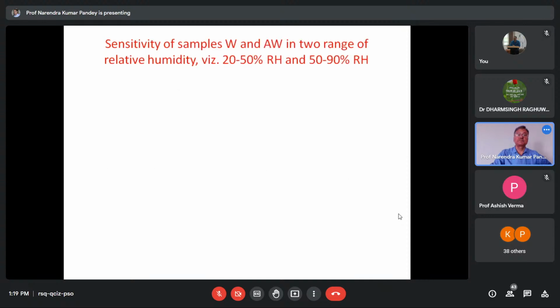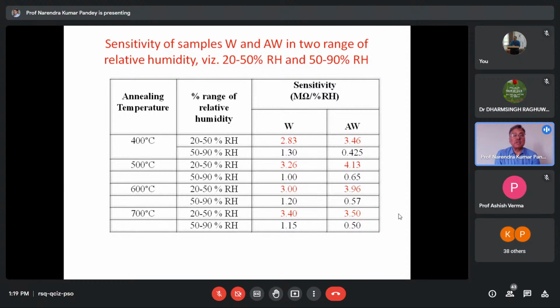And this is the sensitivity chart that you can see. Annealing temperature is 400, with relative humidity ranges of 20 to 50%, and 50 to 90%. Here it is 2.83. Here, if you are adding Ag, then it is 3.46. Generally, you will find that the sensitivity is increasing on loading with silver.